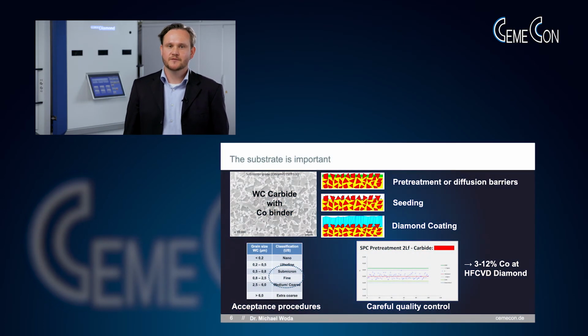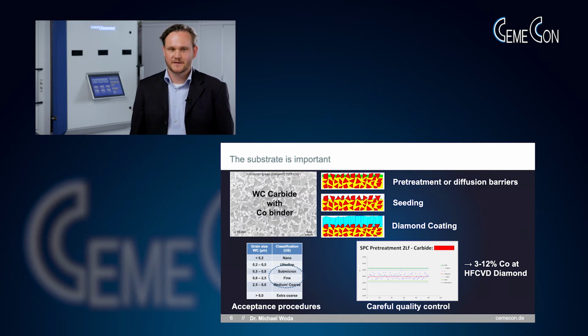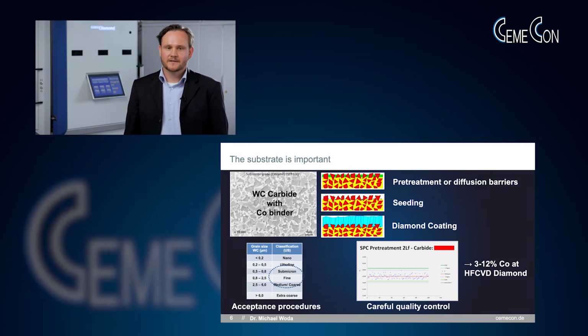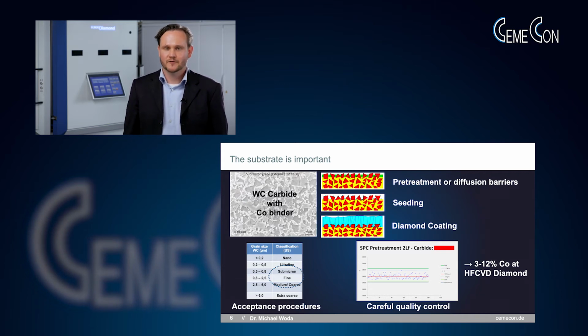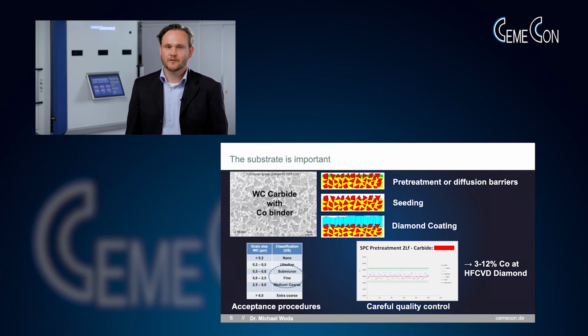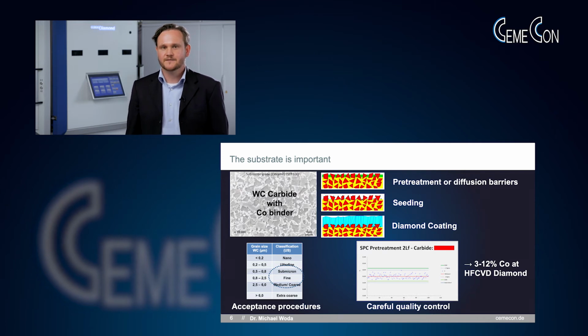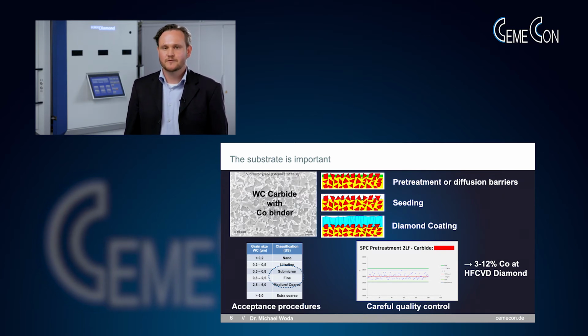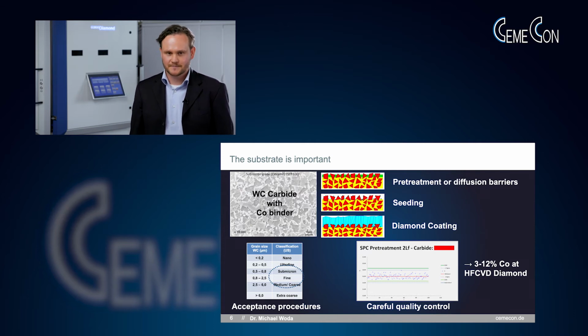Cutting tool industry uses cemented carbide. Typically, tungsten carbide with a cobalt binder is used here. As cobalt in the presence of diamond coating leads to graphitic formation, we have to avoid this process. Thus, we have to apply pre-treatment processes in order to remove the cobalt in the near surface region, or we can apply diffusion barriers. In detail, these processes can be very complex and complicated, especially when we consider that we want to coat more than 200 different carbides on a production level.